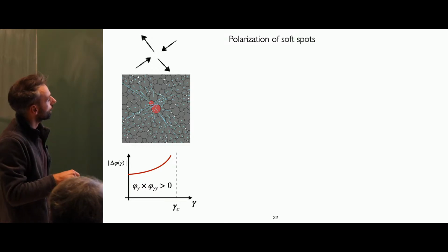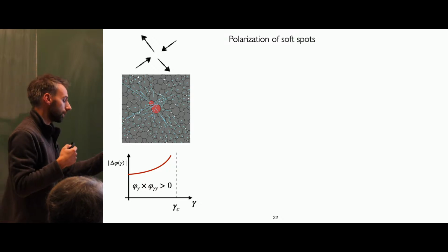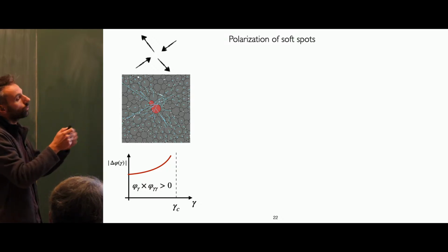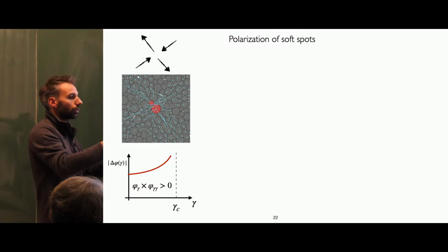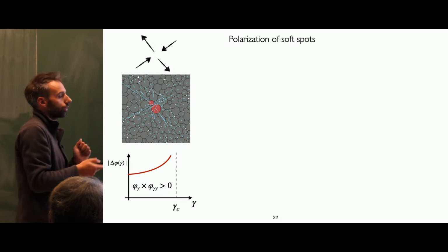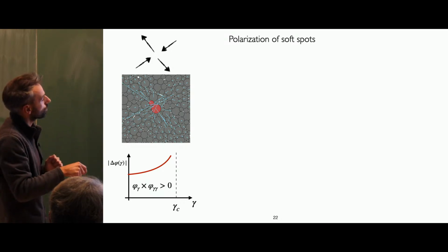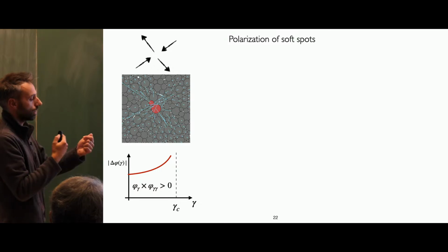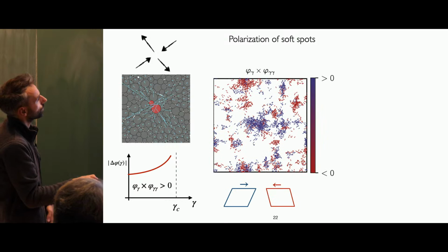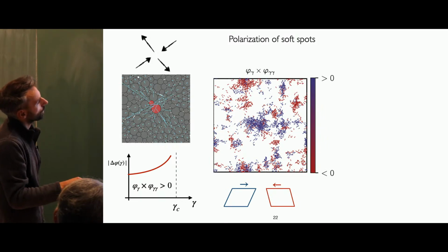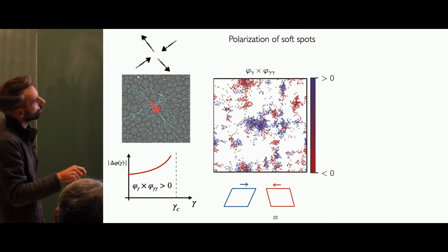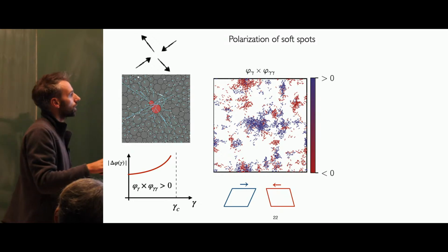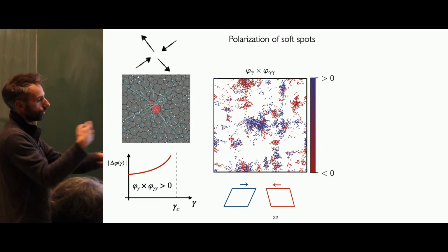And the idea here is to combine coefficients of the strain energy expansion in a sense that if you approach an instability, you know that some of the bonds are going to extend and compress. So at the linear and quadratic level, you should expect that they have the same sign because they will undergo a deformation. And so you can use the product to distinguish which ones are going to be stabilized in one particular direction. And if you do that, it's the same type of information that I showed you, but this time I make a color according to the sign of the product. You can distinguish soft spots that will couple to a positive simple shear and soft spots that couple to a negative simple shear. So you really get a map where you can predict this for a given deformation and on top know the direction of the loading.